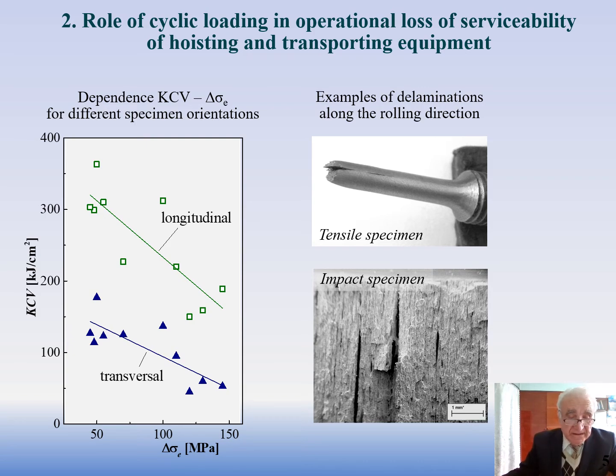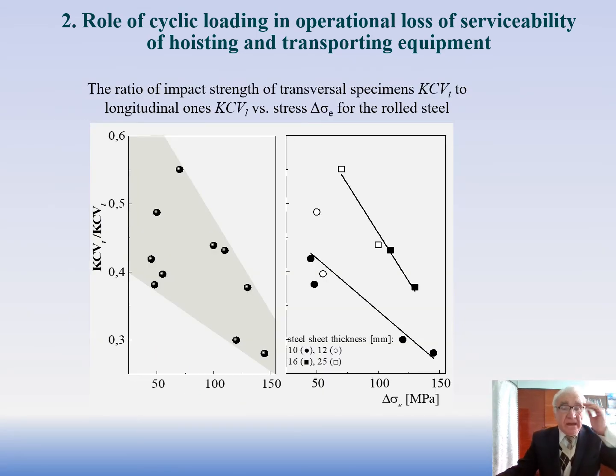In addition, it was shown that delamination along the rolling direction accompanies the drop in impact toughness. This results in different KCV values for specimens cut longitudinally and transversally to the rolling direction. A big difference was revealed between impact strengths of specimens cut in different directions concerning a rolling direction. Impact strength level of transversal specimens was essentially lower in comparison with longitudinal specimens. And this difference was more significant for more stressed steel, that means more degraded state.